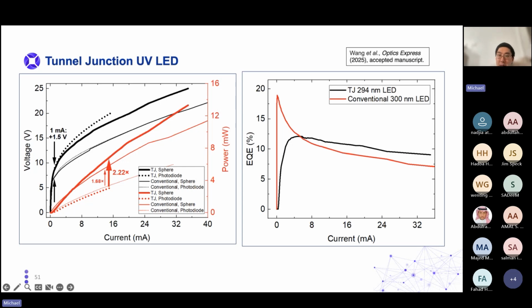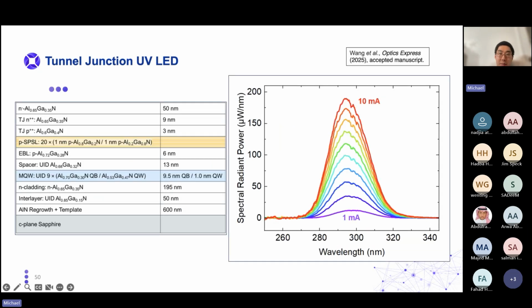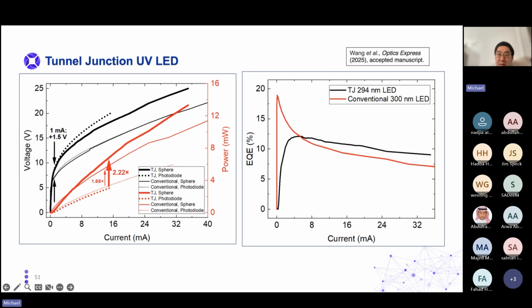So you can see here with the efficiency that we lose the low current efficiency peak due to leakage through the tunnel junction. So these were not actually fabricated. These were quick test devices with indium contacts. So with the scribed indium contacts over here, what happens is some of the current leaks through this top N layer as a parallel pathway to the current that's flowing through the N-type cladding layers. So because of that, we lose this high efficiency peak, but at higher currents, we can see the clear benefit of the fully transparent LED structure with much higher efficiency compared to the conventional p-GaN island LED.